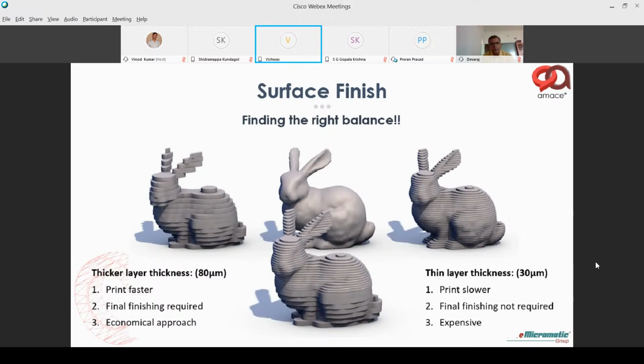This slide shows you about surface finish. What you see on the left side is a very coarse thickness. Imagine we take it as an 80 micron layer thickness. When you want a part which has to be printed fast, we end up choosing a coarse thickness. So this has the advantage of printing faster. You get your final part much sooner, and it's an economical approach. But the problem is the surface finish is very poor.